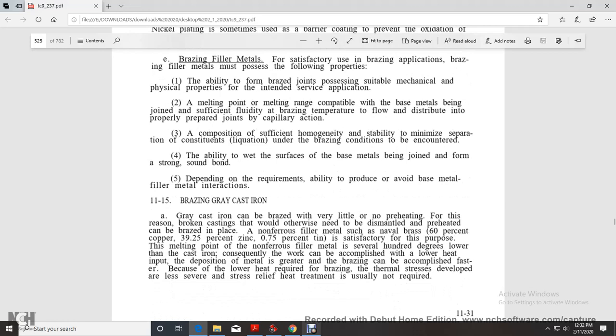11:15 Brazing gray cast iron. Gray cast iron can be brazed with very little or no preheat. For this reason, a broken casting that would otherwise need to be dismantled and preheated can be brazed in place with non-ferrous metals such as naval brass, 60% copper, 39.25% zinc, and 0.75% tin, which is satisfactory for the purpose. The melting point of the non-ferrous filler metal is several hundred degrees lower than the cast iron. Consequently, the work can be accomplished with lower heat input, and the brazing can be accomplished faster. Because of the lower heat required, thermal stress development is less severe, and stress relief heat treatment is usually not required.